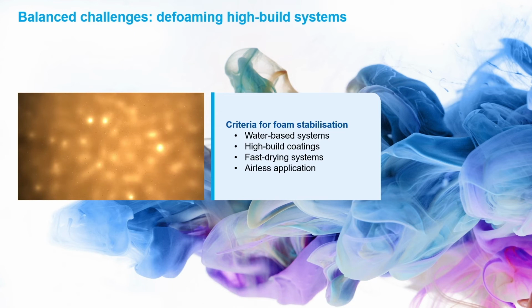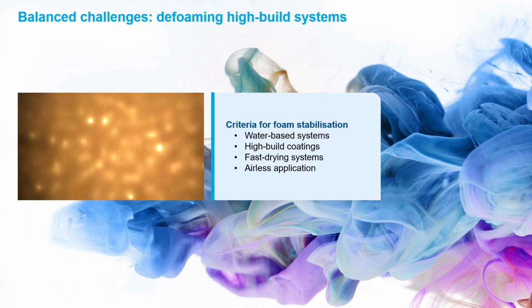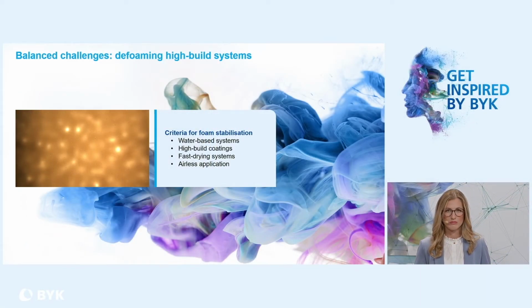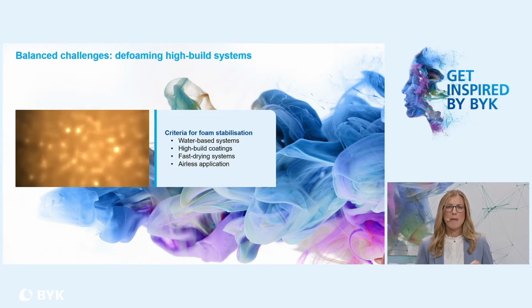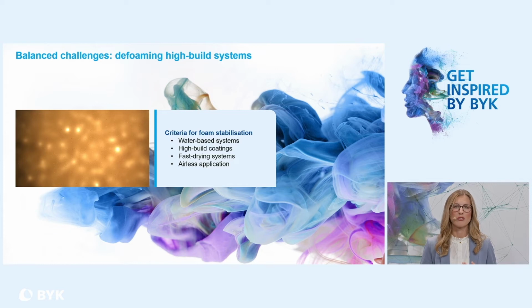So this entrapped air in the coating will lead to surface defects and therefore to the loss of corrosion resistance. In the protective market, solvent-borne coatings are still dominating, as we are aware that there are several challenges that have to be solved if water-based formulations are used. And one of them is foam. So defects caused by foam make it much easier for the water to penetrate the coating and to reach the metal surface. This results in the corrosion of the metal and/or in disbonding of the coating.